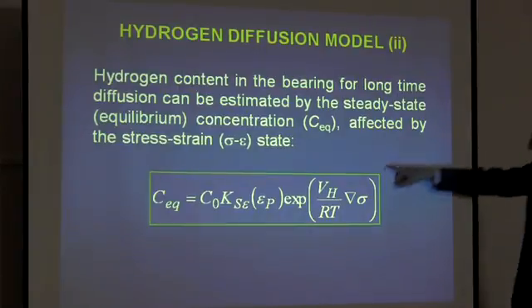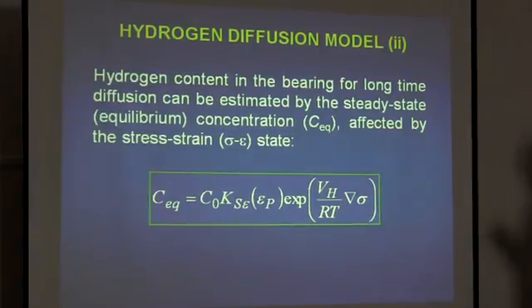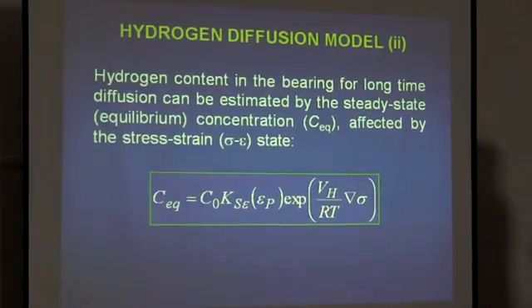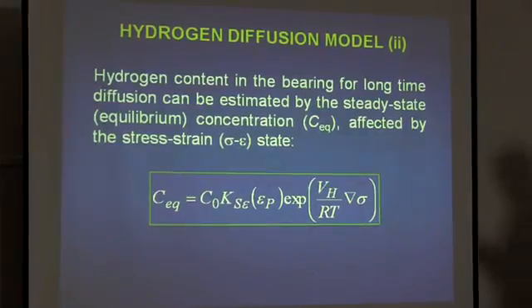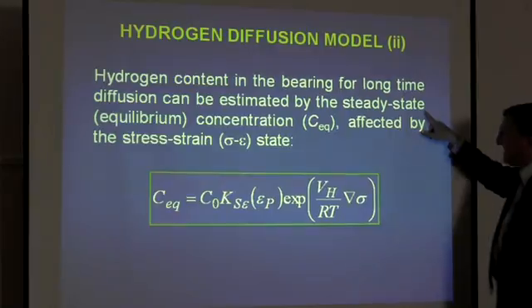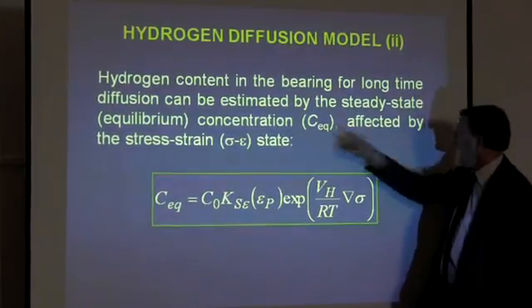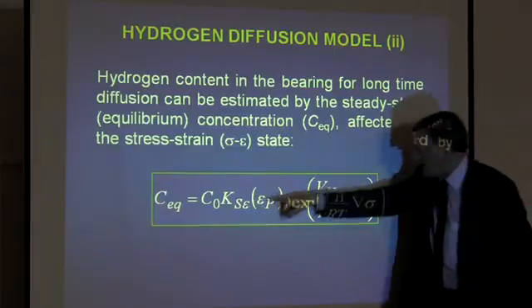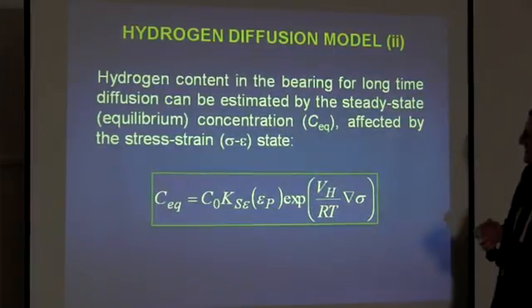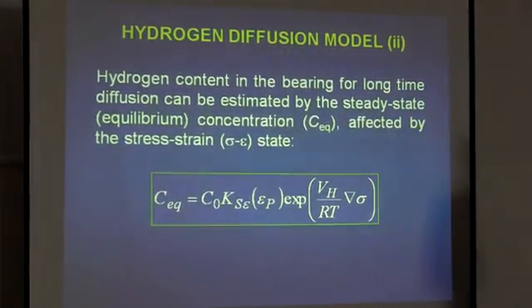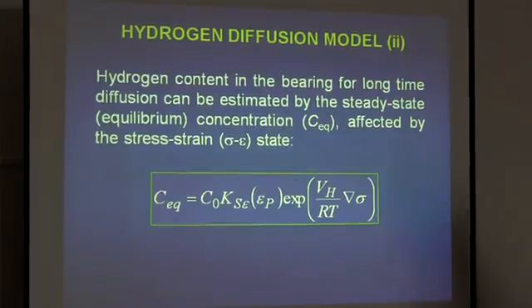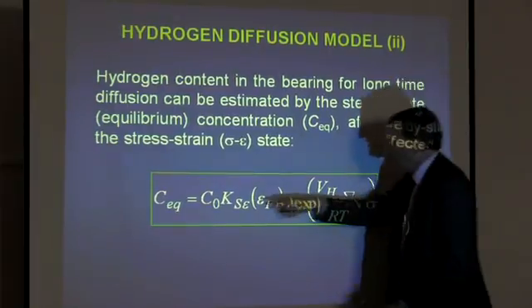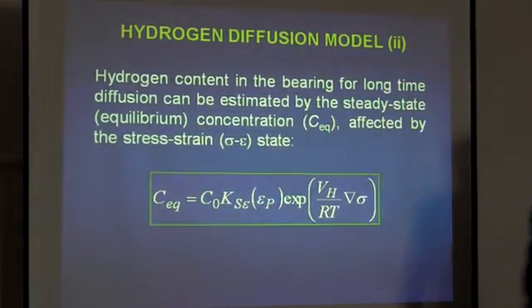Then the hydrogen diffusion model contains this equation for the equilibrium concentration. Hydrogen content in the metal, for a long time, infinite time in theory, diffusion can be estimated by the steady state equilibrium concentration Ceq, affected by the stress-strain state. This is a function of the gradient of hydrostatic stress, Maxwell-Boltzmann type, and the solubility is also included with the strain-dependent term. And C0 is the equilibrium concentration of hydrogen in the metal free of stress.